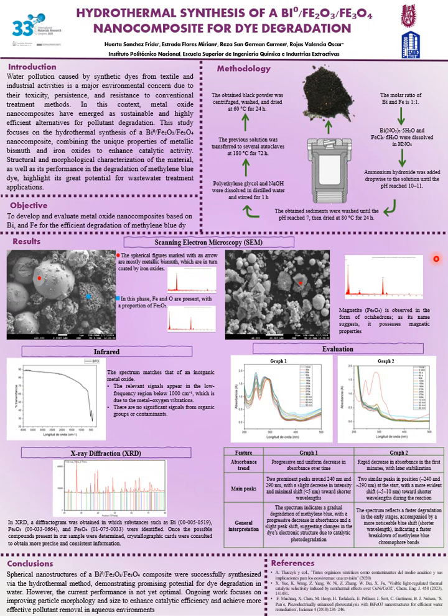Results: scanning electron microscopy (SEM). At the red point, the spherical figures marked with an arrow are mostly metallic bismuth, which are in turn coated by iron oxides. At the blue point in this phase, Fe and O are present, with a proportion of Fe3O4. Magnetite Fe3O4 is observed in the form of octahedrons. As its name suggests, it possesses magnetic properties.